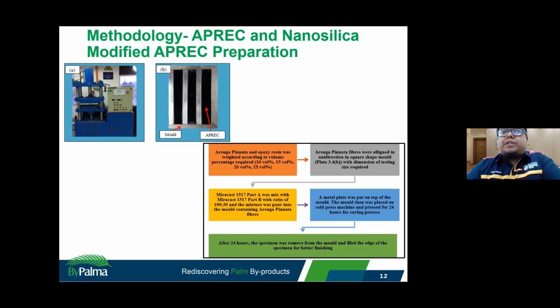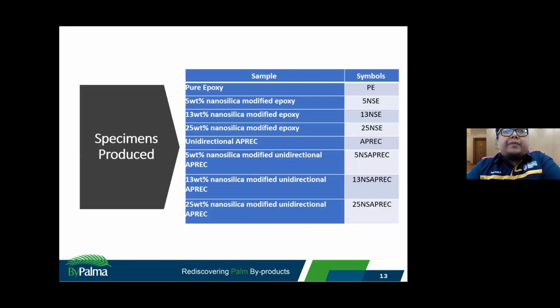Okay, after 24 hours, the specimen was removed from the mold and we filed the edge of the specimen for better finishing. Okay, so this is the specimen produced for this study. I have around eight types of specimen for this study.